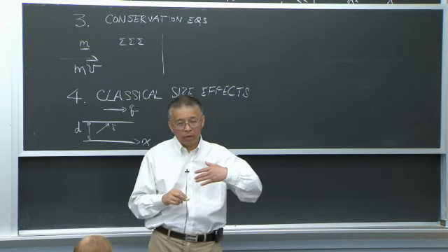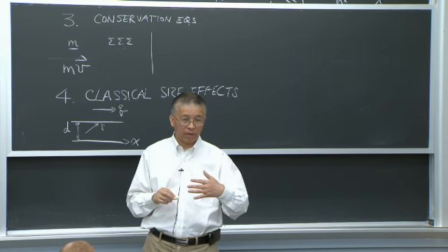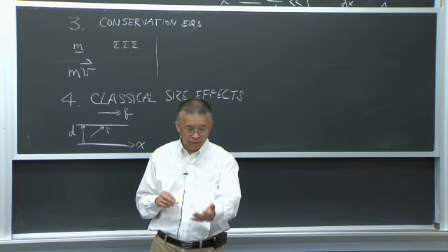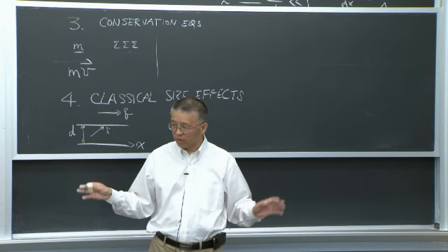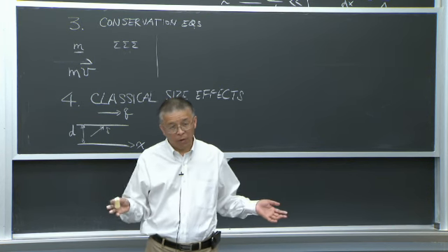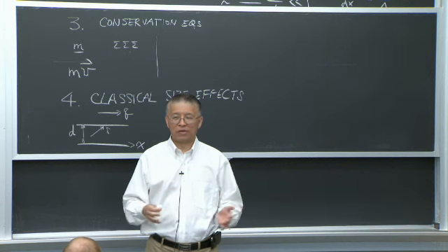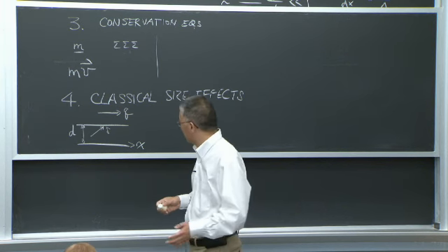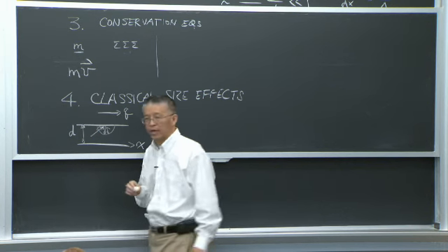Of course, once they collide with the boundary, they will be scattered, reflected, and that depends on the boundary condition, for example the roughness at the boundary. We know when light hits a surface like your table here, it's a diffuse scatter. If you put a mirror there, it's specularly reflected. Reality may be somewhere in between, and in fact, still nobody really knows what's happening at the boundary. So the assumption we'll make first is diffuse, so isotropically scattered into all directions.